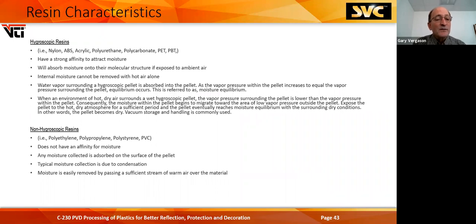These are some characteristics of the hygroscopic resins and non-hygroscopic resins. Some will absorb moisture. Polycarbonate is one like that. Moisture will go through it. When we're doing polycarbonate housings for the automotive industry, we actually put down an HMDSO base coat, aluminum layer, HMDSO top coat. So we sandwich that coating in between two HMDSO layers.